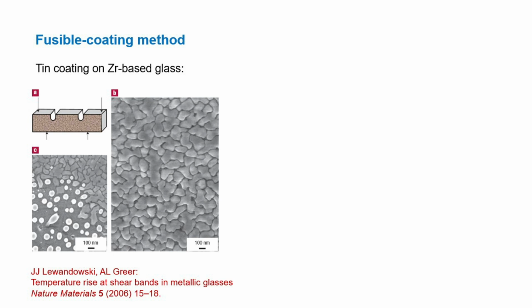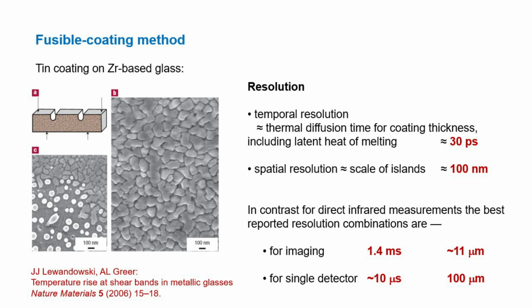So with that as a background, we're using the tin as our detector, and it's a wonderfully good detector because you can work out a typical time for things to happen, the thermal diffusion time, so it gives you the time resolution of our heat detector. And the scale of this gives us essentially a spatial resolution of our heat detection. And those compare extremely favorably with doing it by direct measurements using infrared. So people have been doing this, but this is streets better. And I like to think that possibly of anything I've ever done, this must be the experiment that might be closest to one that would actually interest G.I. Taylor, because it's just a nice, neat little thing of letting the tin do the work for you.